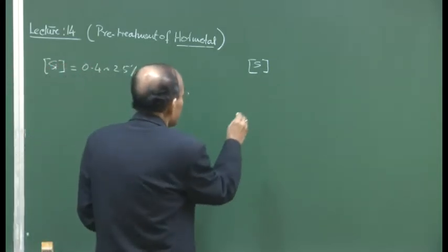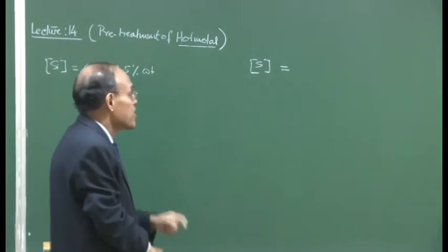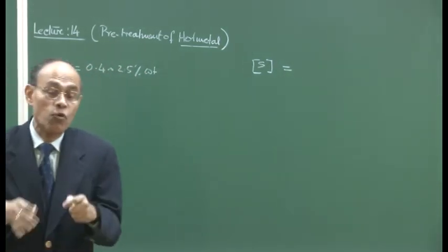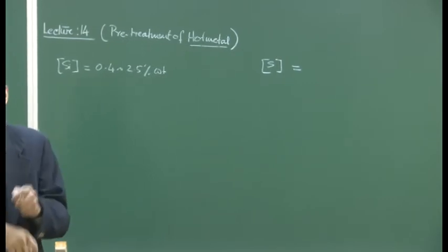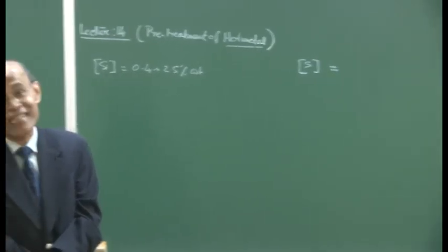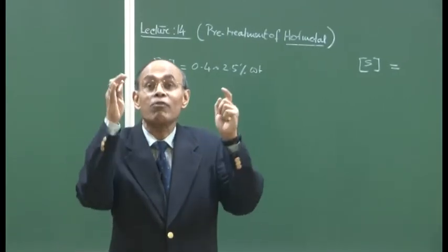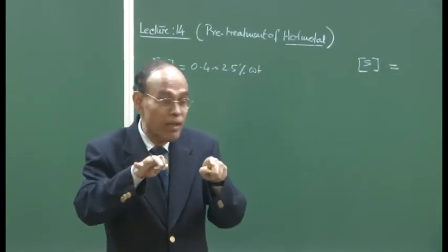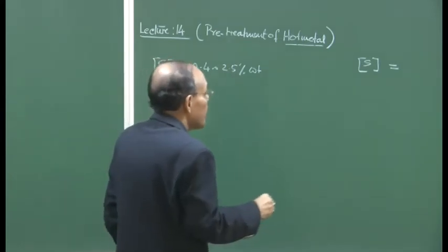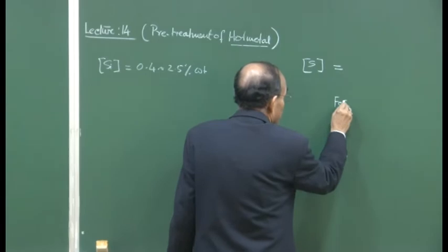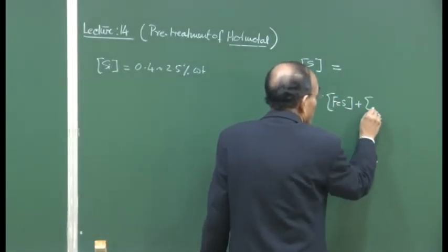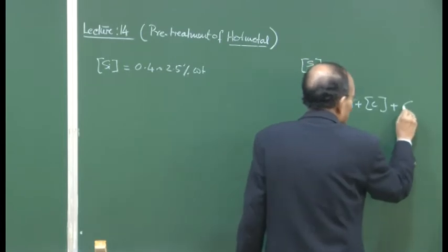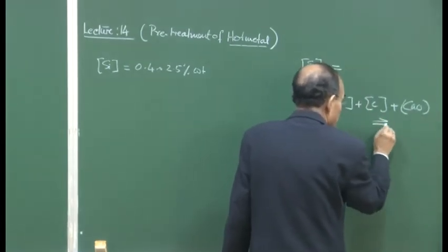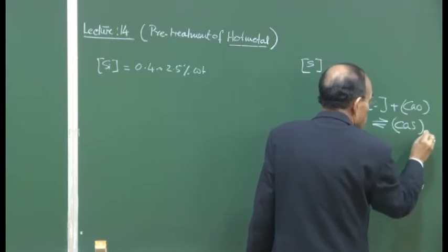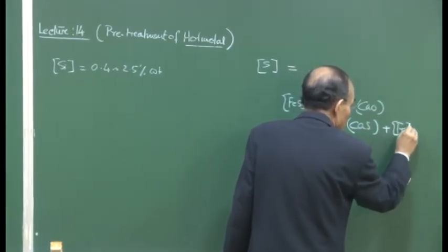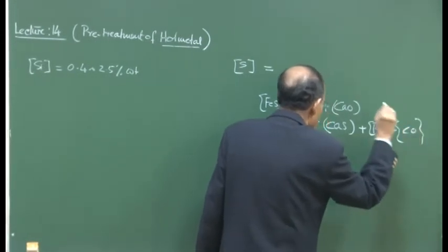Now, the sulfur in hot metal also can vary. The atmosphere is reducing, but we require a highly basic slag, and we may not be able to maintain a very highly basic slag, because very high basic slag means we have a lot of lime in it, and we need to keep the slag fluid. Desulfurization, as I have written the equation in molecular form, is sulfur and carbon dissolved in hot metal, and then we have calcium oxide, which is in the slag. So it is a slag metal reaction, and that gives us calcium sulfide going to the slag, iron produced in the metal, and CO, which evolves as gas.